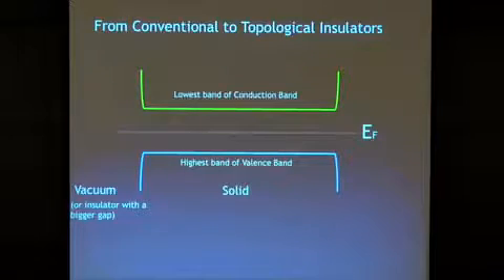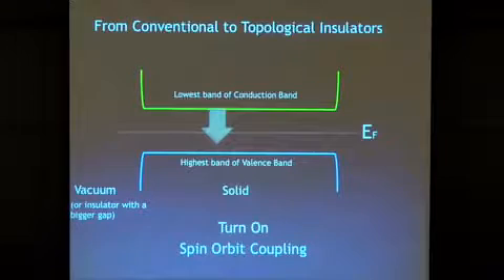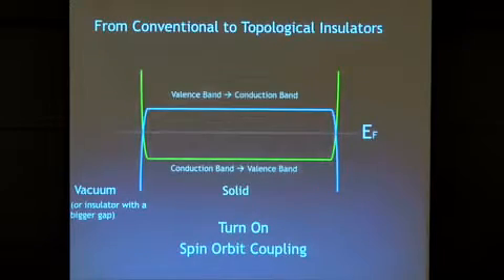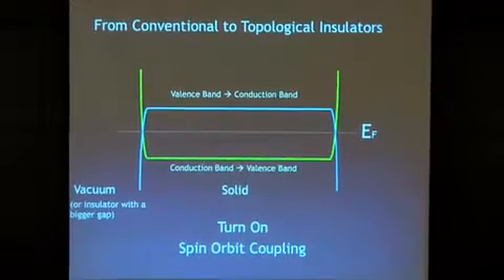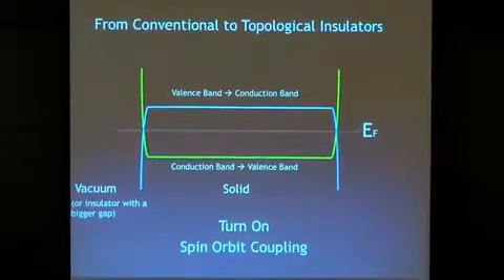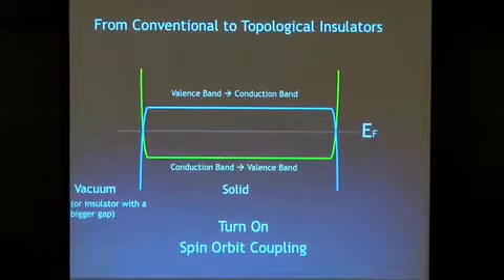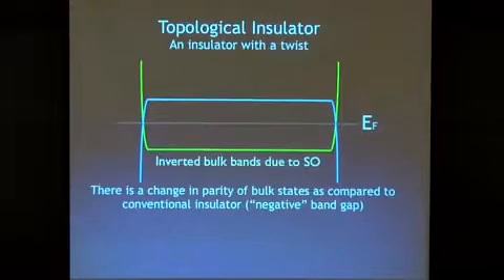Now imagine that I had a knob in the lab that I could turn up the spin-orbit coupling, and I had a way in which I can turn the states that were once conduction band into the valence band, and those that were valence band states into the conduction band. Now, I still have an insulator, but I have created this twist, if you like, in the electronic structure of the material. Now, if you think about sandwiching this sample in between another sample which has a larger energy gap, you can't really get rid of this twist very easily. And this is the basic idea of a topological insulator.